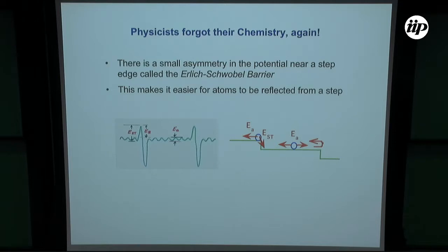This was observed experimentally by Gert Ehrlich at Illinois. I don't know if you ever knew about him. He was a giant in surface physics. He worked on atomic emission microscopes where he did a lot of the initial calculations of diffusion constants of atoms on various surfaces, tungsten and things. And also this was found by Schwoebel in a density functional calculation, because he realized that there was a slight difference in going down a step or up the step for an atom, somehow the distance at some point is larger once the atom is going down the step. But that's not so important. But the main point is, how does this small effect, namely the Ehrlich-Schwoebel barrier, cause the mound formation?